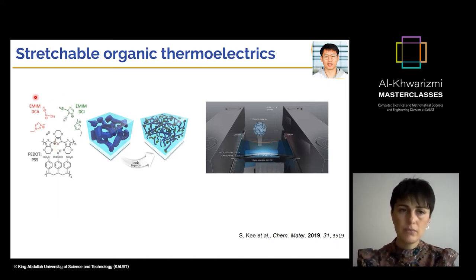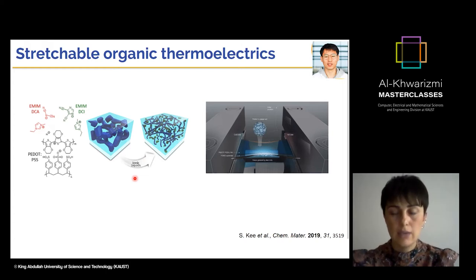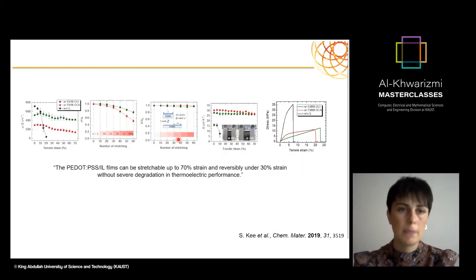And we know that ionic liquids have shown before that they can dope or de-dope and control the microstructure and also give potential stretchability as well. So what we did here is we mixed these ionic liquids with PEDOT in order to control the morphology and the thermoelectric properties. And in the end, we achieved stretchable devices using PDMS as the substrate, basically. So in thermoelectric devices, your conductivity sigma, or Seebeck coefficient, or totally power factor, are the figures of merit that you usually look for the performance.